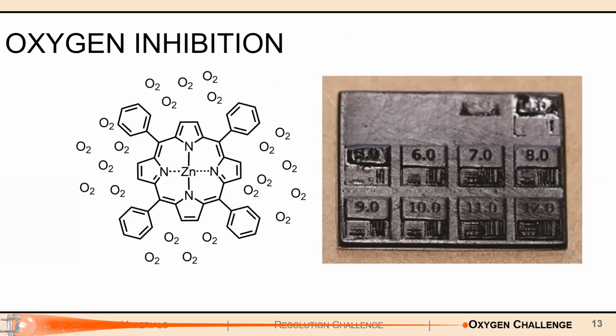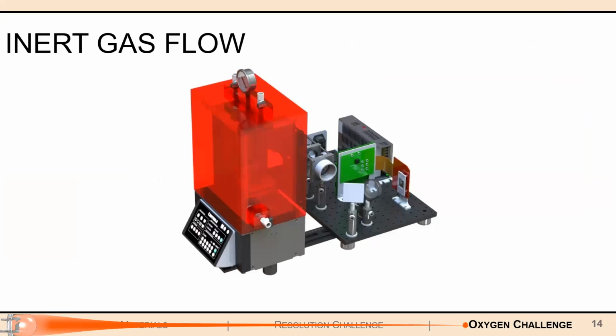And the end result of that is that essentially interferes with your polymerization reactions, and the prints don't go to completion. As you can see right here, where we're getting the 1 and 2 seconds don't show up, and even at like 5 seconds, we're struggling to get a lot of detail on this resolution print. Thus, the solution that we found was to use inert gas flow.